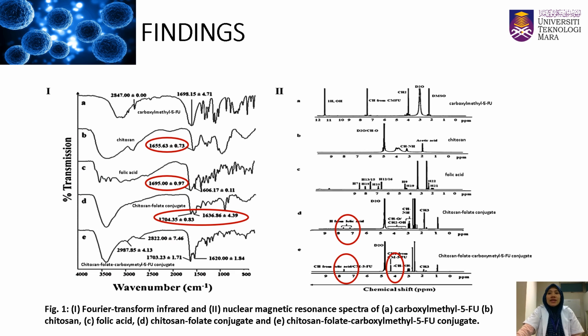Now let's take a look at my findings. In this study, you can see that folate and CMFU have been successfully conjugated to chitosan. Conjugates are characterized by FTIR and NMR. The presence of folate in chitosan was detected at the 1704 FTIR peak and at 7.2 and 7.7 ppm of the NMR peak. Coupling of CMFU to the chitosan folate conjugate was confirmed by the NMR signal at 4.3 and 7.7 ppm.